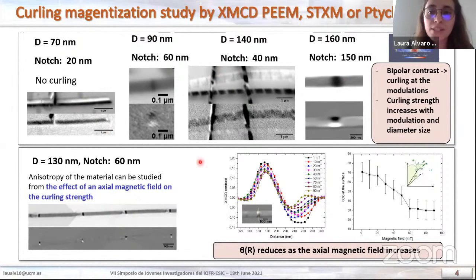So just to summarize all these images, what we observe is that at the chemical barriers, we have a bipolar black and white contrast. That means that the magnetization is curling around the wire axis at the chemical barriers, whereas in the rest of the wire, the magnetization is axial along the wire axis. So this is the first conclusion. These nanowires have curling magnetization at the chemical barriers, and then we need to access this curling to fully understand it. So the first approach we take is to apply an axial magnetic field along the nanowire axis to reduce this curling.